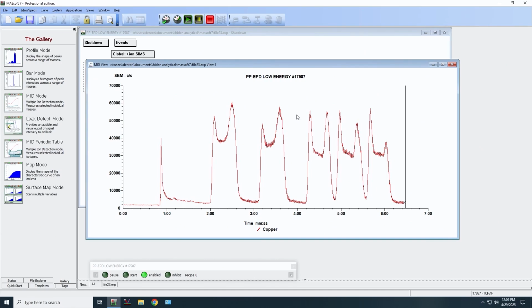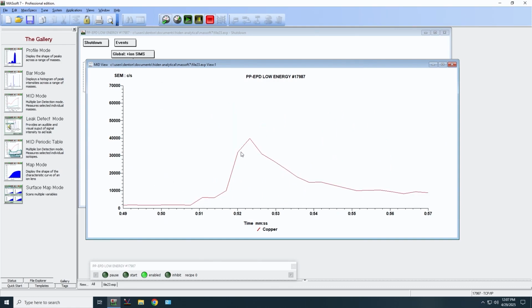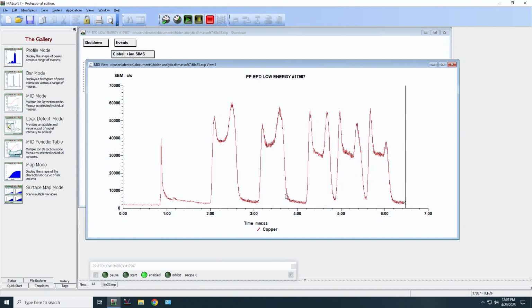The other nice thing about ion beam etching is that it's very repeatable. Even if you just run on time alone, you will get something like 1% error or better. So I could even just run this on time. I can say, okay, from this point of shutter open, which is at 51 seconds, up until 4 minutes, that gives me 3 minutes and 9 seconds. I'm just going to etch by time, and you will get that within 1%, which is probably sufficient if your goal is just to do SEM imaging of